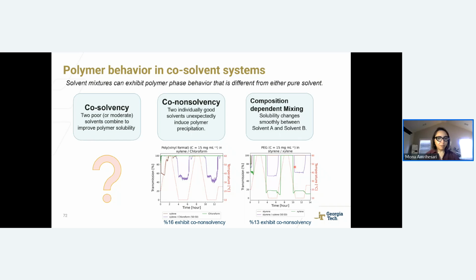13% of these experiments exhibit composition-dependent mixing, meaning that the solubility changes smoothly between solvent A and B. Sorry, this label is not matching what we were talking about, but this is more composition-dependent mixing. As you can see here, one of the solvents is on the top, the other exhibits UCST behavior, and the co-solvent system is between these two, kind of linearly matching.